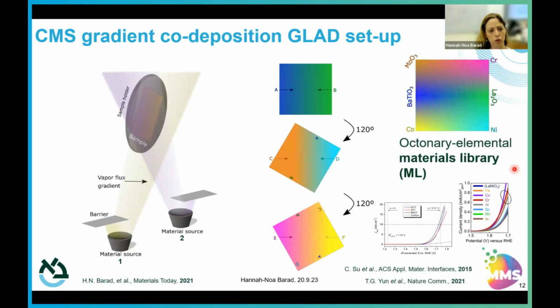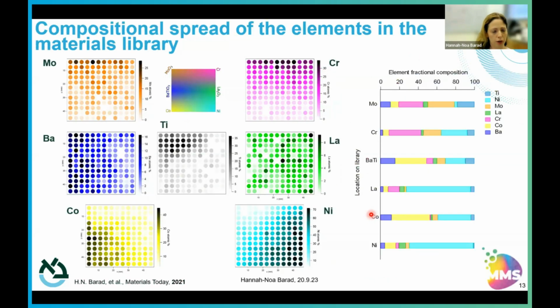So some of the source materials had more than one element, as you can see, barium titanate or lanthanum oxide. And these materials were actually chosen because they had shown high activity individually, each individually, for oxygen evolution, which is what we were trying to use as a reaction for proof of concept. So, of course, if we look into the compositional spread, we are expecting to see differences. So indeed, we do.